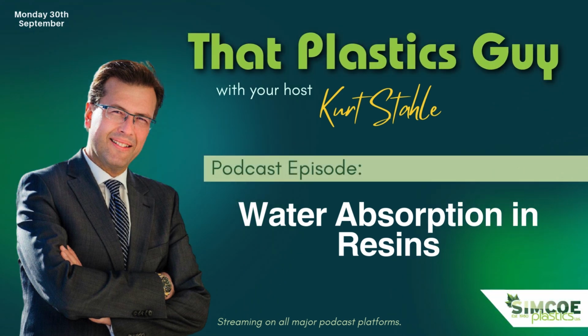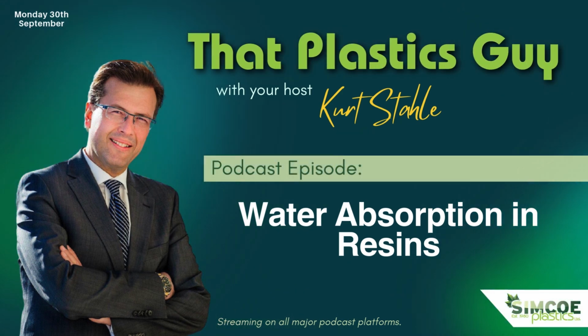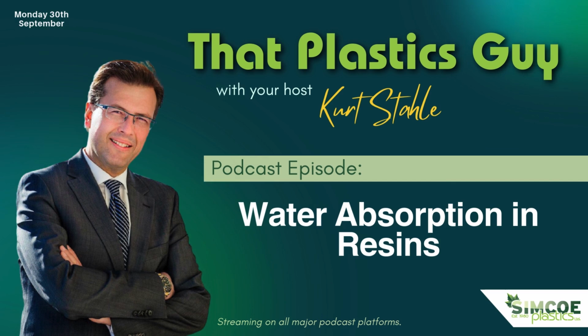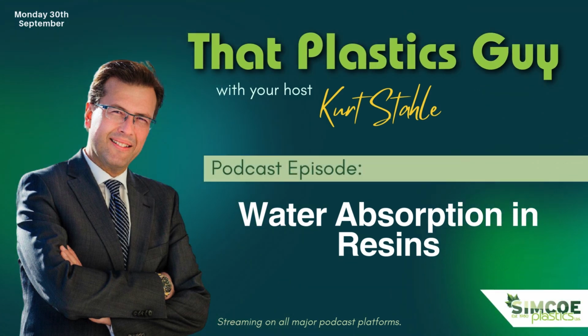And I wonder if there's anything else. No, not too much there. I think the last one I'm going to give you, your typical GPPS, crystal polystyrene, the dry moisture level, 0.01%, maxes out at 0.04%. Again, doesn't sound like a big deal, but if you want to increase your success of having that perfectly cosmetic part, reduce your problems molding, a hot air dryer on top of the machine would be a very, very good option.